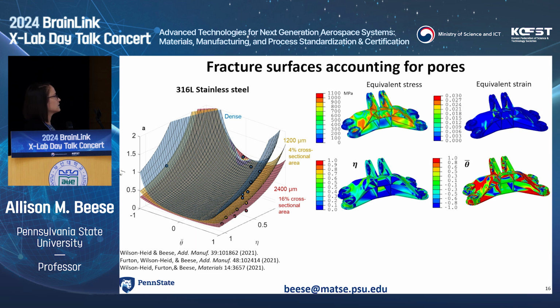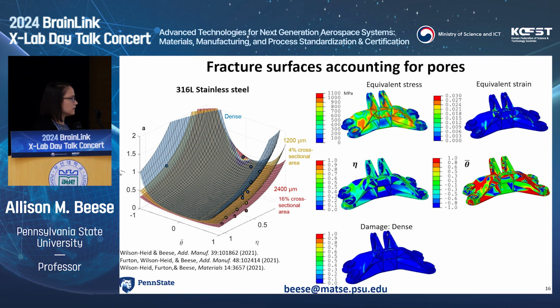So if we take a look at this blue one, for every point we have a unique location of our theta bar and eta, so we have a different location here, and we have some stress and strain that we've reached. So we want to know how far am I from my fracture surface. If I'm really far away, we're going to say that damage is 0. If I'm right on that fracture locus where I'm going to fail, damage is 1. So what do those contours look like? This is what these look like.